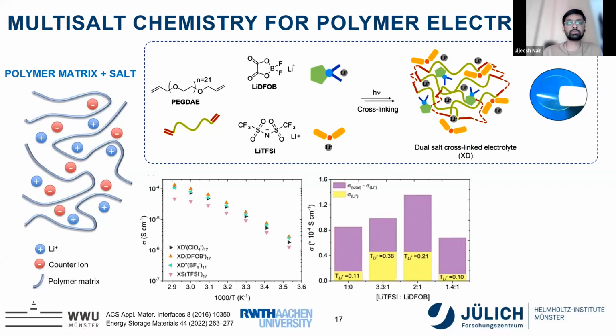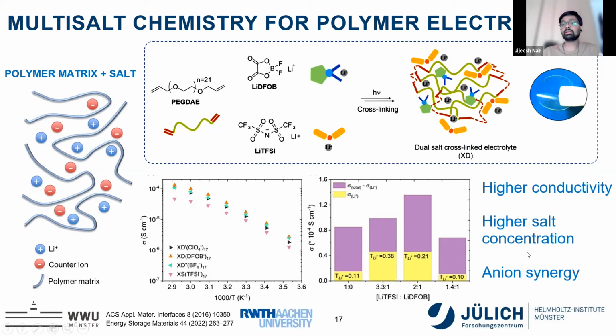adding the second salt, whether it is applicable to different systems, for example, lithium perchlorate, DFOB, LiBF4, LiTFSI, etc., you can increase the ionic conductivity. And moreover, you can increase the ion transport, the transference number, even 3 times increase as compared to a single system. Besides, when you mix and match these different anion systems, you can increase the conductivity, you can increase the salt concentration. For example, if you are using only TFSI, at certain level, you cannot increase further the TFSI addition, because it will not solubilize, or it will increase the viscosity.